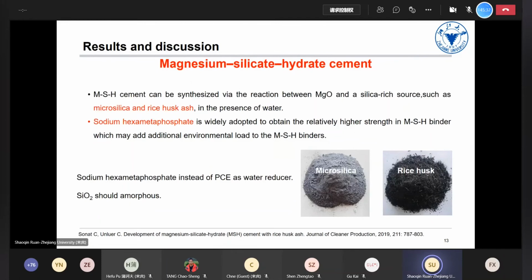Then there is magnesium-silicate-hydrate cement. Magnesium-silicate-hydrate cement can be synthesized by the reaction between MgO and a silica-rich source, such as microsilica and rice husk ash, in the presence of water. And this salt, sodium hexametaphosphate, instead of PCE, is used as a water reducer. However, when you use this water reducer, it may add additional environmental loads to the M-S-H binders.